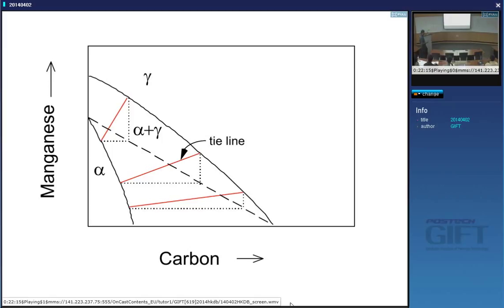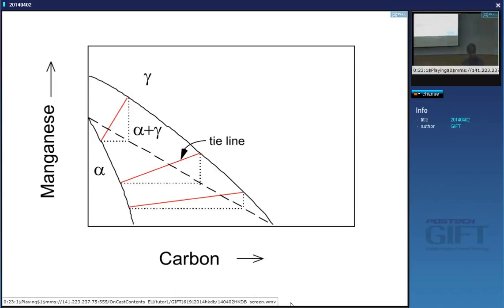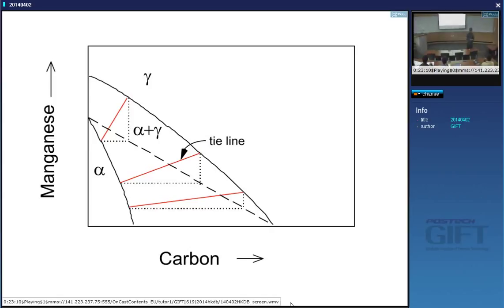In all our teaching, we are assuming that C-bar remains the same far away from the interface. If C-bar changes, then the tie line will change, and eventually the final tie line will pass through the alloy — this is called tie line shifting. That's a very good point. We are assuming at the moment that we only have a small amount of ferrite forming, so C-bar is not influenced.